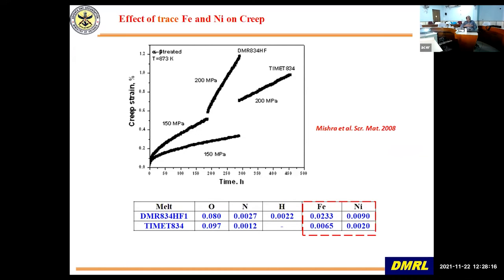Here I am showing you the very large effect of very, very small amounts of iron and nickel. You can see this IMI 834 was melted in DMRL with master alloy and other combination, which got iron and nickel in this range in the final composition, whereas the imported alloy had lower amounts of iron and nickel. You can see the very small amounts: this is 65 ppm, this is only 20 ppm, whereas this is 233 ppm, parts per million, and this is 90 ppm. And you see the creep properties were measured at 150 MPa as well as 200 MPa load level at a temperature of 873 degrees Kelvin, that is around 600 degrees centigrade.